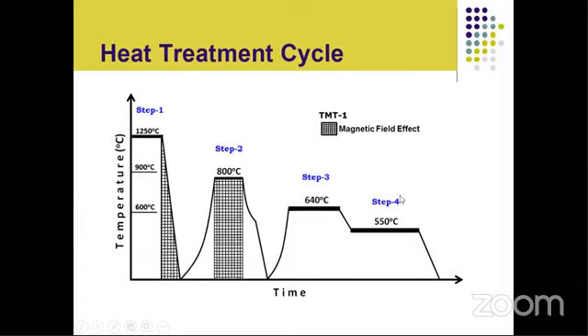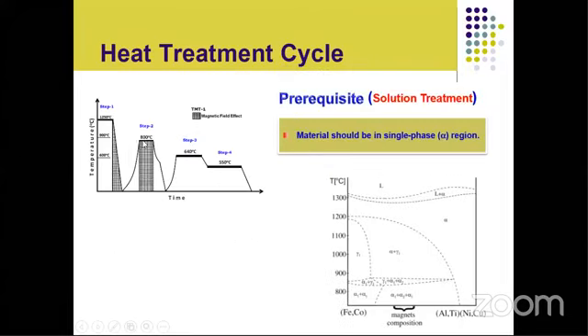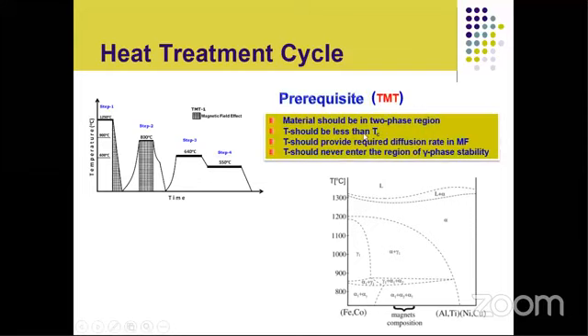So if this situation is achieved, then we have very good coercivity of the magnets, and of course good magnetization could be achieved. So for these three steps, which are solution treatment, thermomagnetic treatment, and step aging, we have some prerequisites. Like for the solution treatment, the material should be in the single phase, that it must be in the alpha phase, and then it should be quenched. Next, TMT, thermomagnetic treatment. For thermomagnetic treatment, material should lie somewhat here in the two-phase structure. Material should be in the two-phase region.